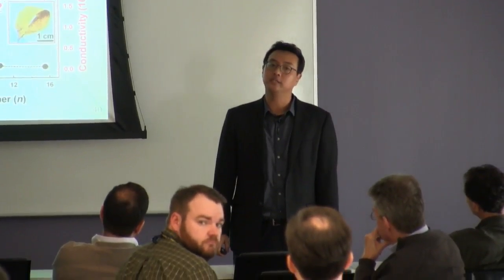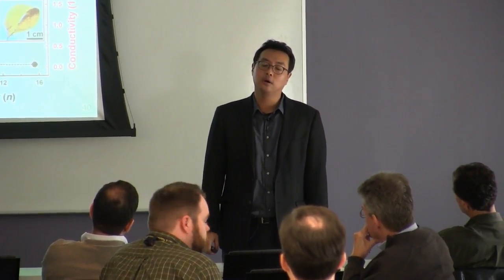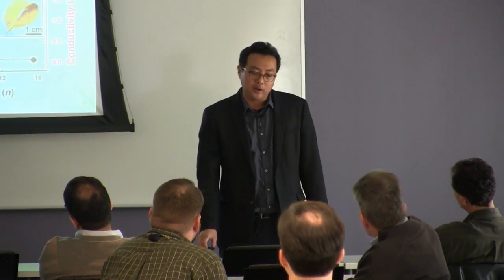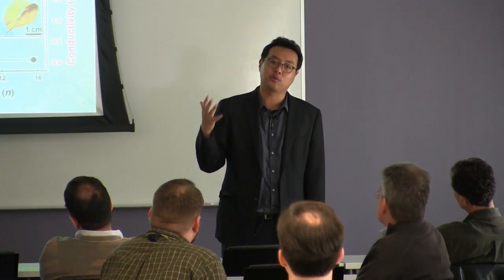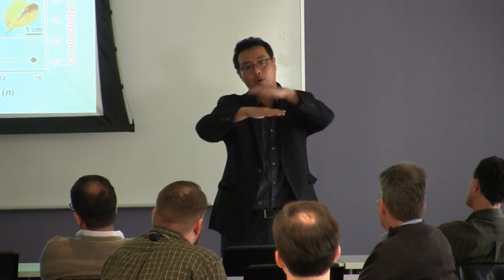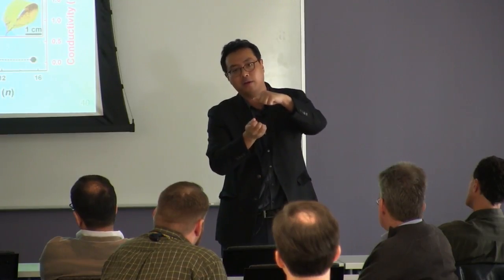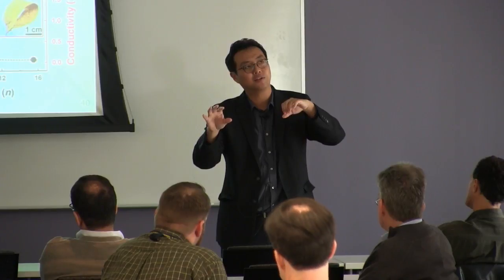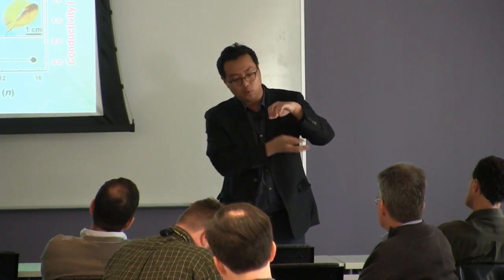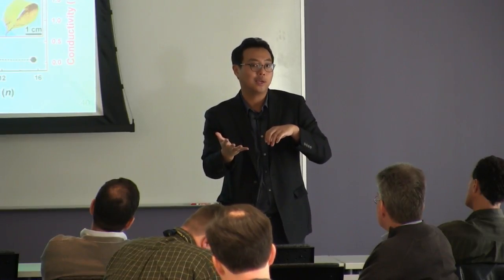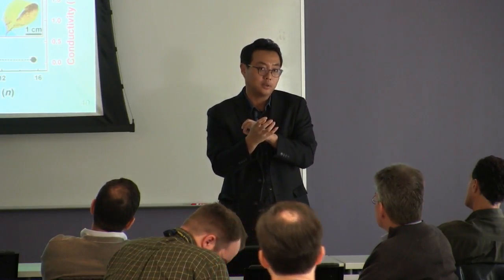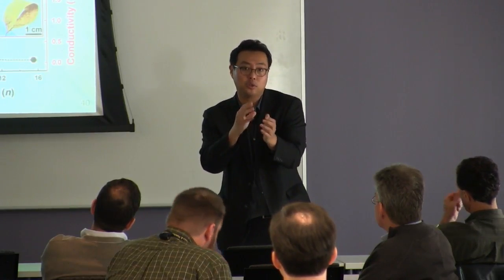Is it a challenge to disperse these particles over the entire paper? No, actually, it's pretty easy. Generally, before this work, people used polyelectrolyte. For example, let's say gold nanoparticle. First prepare the charged gold nanoparticle, then prepare another charged polymer. Then we deposit nanoparticle, polymer, nanoparticle, polymer. In between the nanoparticle layers there are bulky polymers, so the electrical conductivity is not so good. Now we remove all of this bulky polymer and bulky ligand, so we can decrease the distance between the gold nanoparticles. That can maximize the electrical conductivity and communication between the nanoparticles.